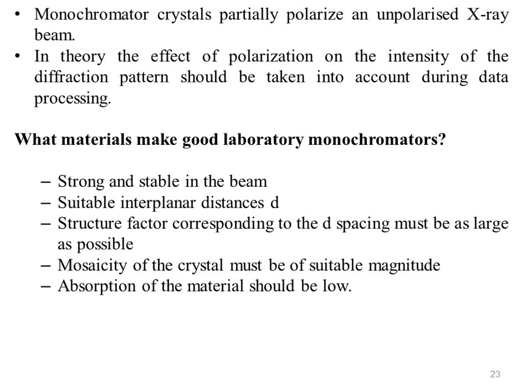By contrast, pyrolytic graphite monochromators with their wide band will pass both K alpha wavelengths but not K beta, for which the Bragg angle is considerably different. Monochromator crystals partially polarize an unpolarized X-ray beam because the operating principle is one of Bragg diffraction. In theory, the effect of polarization on the intensity of the diffraction pattern should be taken into account during data processing, but in practice the correction effect is relatively small and often ignored.